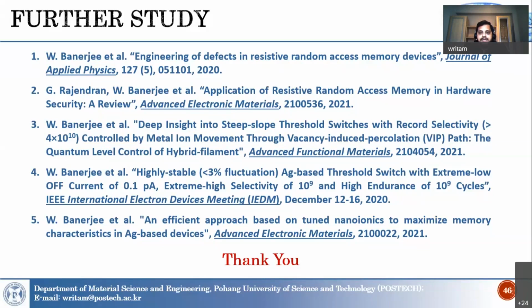I'm not very sure exactly how many vacancies there are, but it is confirmed that when you have low current like 1 nanoampere, the number of oxygen vacancies is much lesser compared to when you have current levels like more than 1 microampere. So the thickness of the channel is also much lower in that case. This was based on that assumption. I do not have pure quantification of those values, but the work was conducted with that approach because our main objective was to get the localization of the silver path.